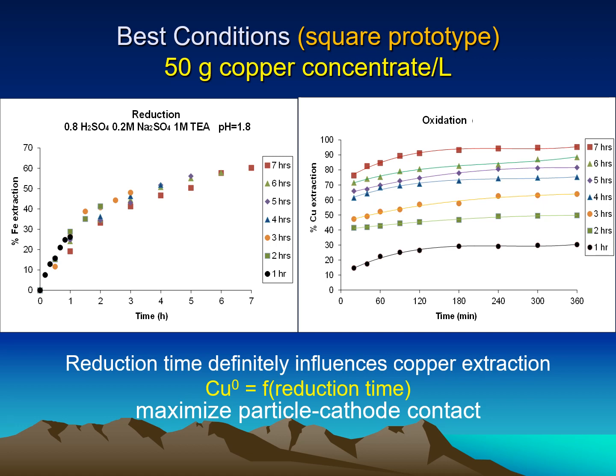And as you can see, at the very beginning, the initial 5 or 10 minutes, there's a very large amount of instantaneous dissolution. This is actually from the copper that's reduced all the way down to copper metal, and the rest of the remaining copper is leached a little bit more slowly, which is actually from the chalcocite. The reduction time definitely influences the copper extraction, and if we can maximize the contact between the particle and the cathode in the reduction stage, this optimizes the process.